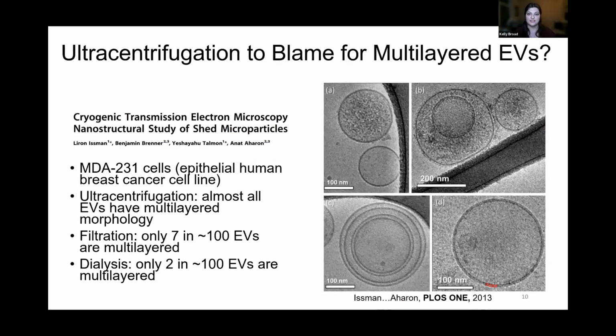However, this publication in 2013 found that using dead-end filtration and dialysis greatly reduced the fraction of EVs with a multi-layered morphology. They concluded that cryo-EM sample preparation was not the source of the multi-layered EVs, suggesting that the multi-layered EVs were an artifact from ultracentrifugation, forcing smaller vesicles into larger vesicles.